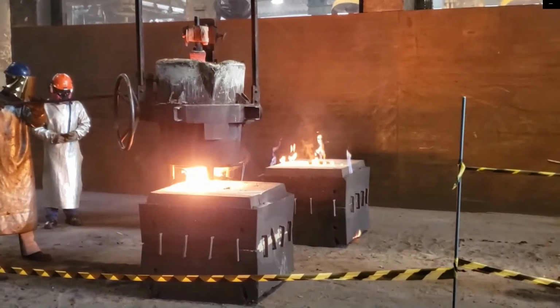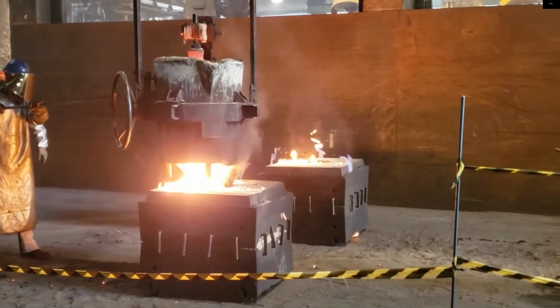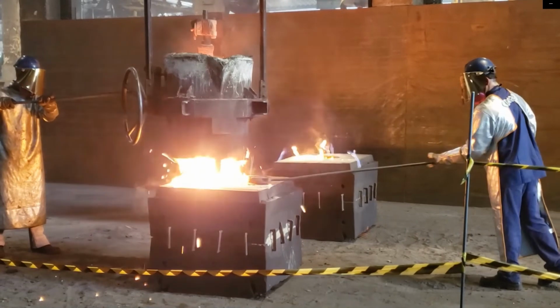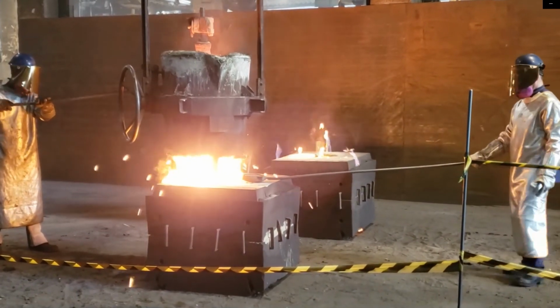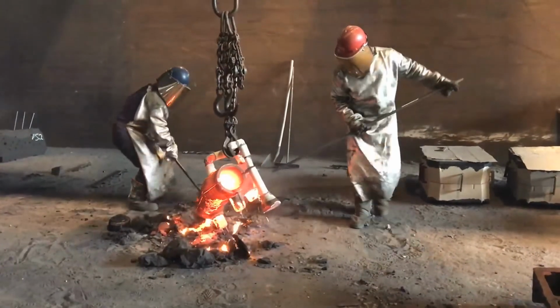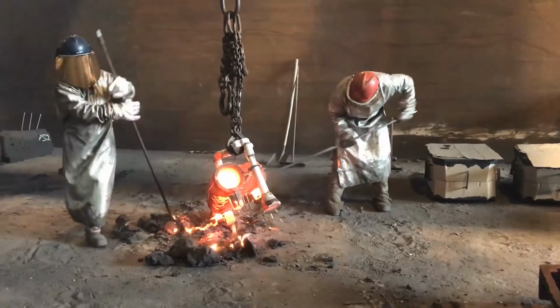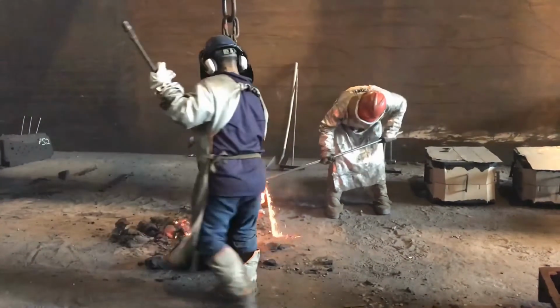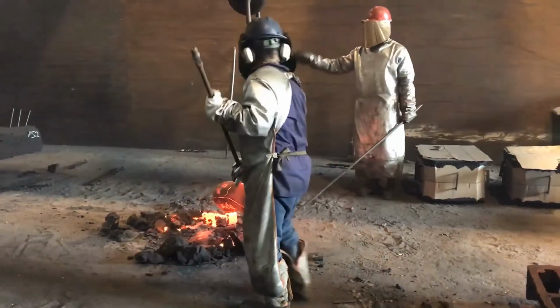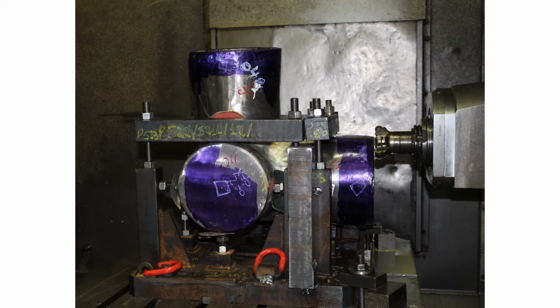Molten steel is poured into the molds, with real-time testing to confirm the alloy. Test blocks are created from each pour for destructive testing. After a time, the castings are demolded, sand is shaken off, and quenching and tempering may be performed as per ASTM and/or project specifications. Non-destructive examination, including RT, UT, and MT, are conducted on the as-cast part to meet project-specific